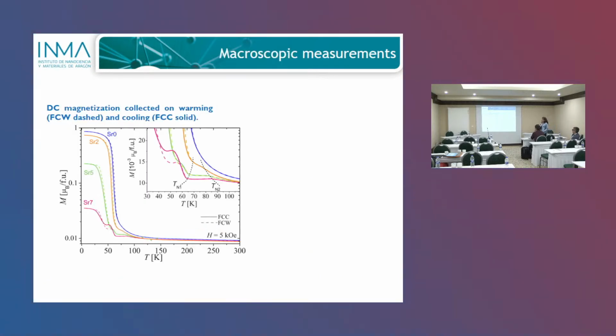And the first characterization of the system was the magnetic measurements, and we immediately can see that the effect of adding strontium is quite impressive. There are a lot of things going on here when you start adding strontium. So the parent compound has this typical ferrimagnetic type of behavior, but already for a 2%, which is the orange curve, and 5 and 7%, you start decreasing. Here is a logarithmic scale in the magnetization. You start decreasing this magnetization, and also you start